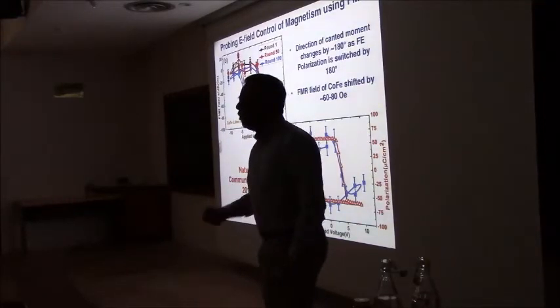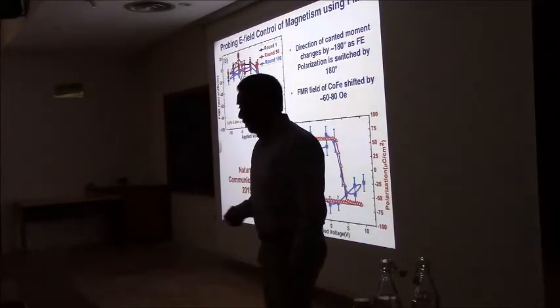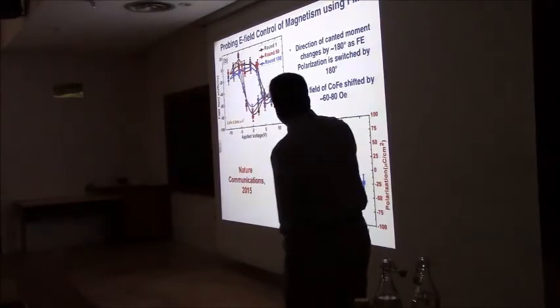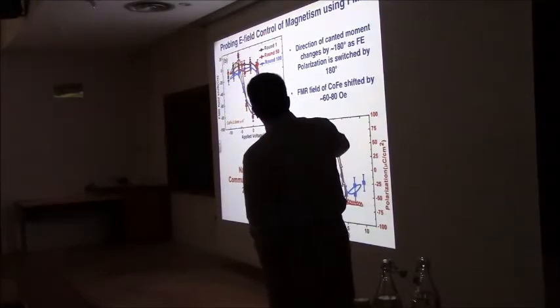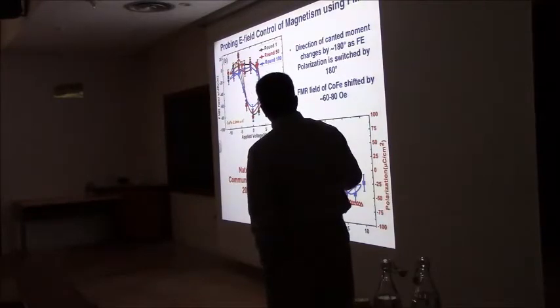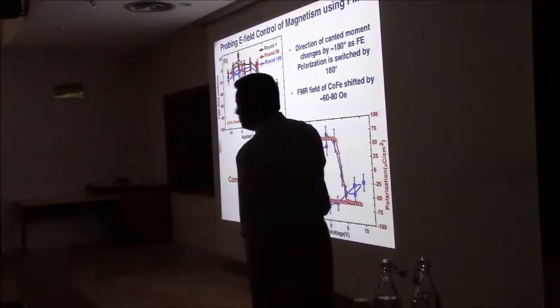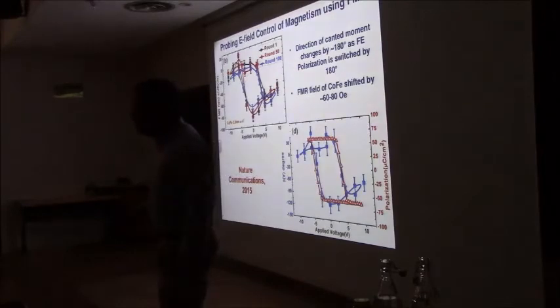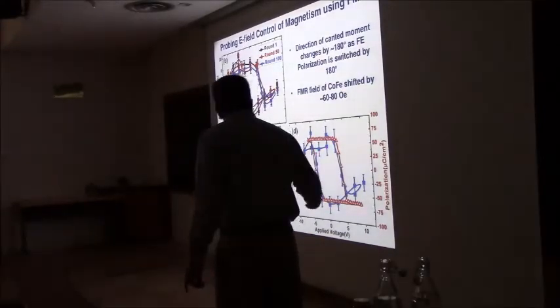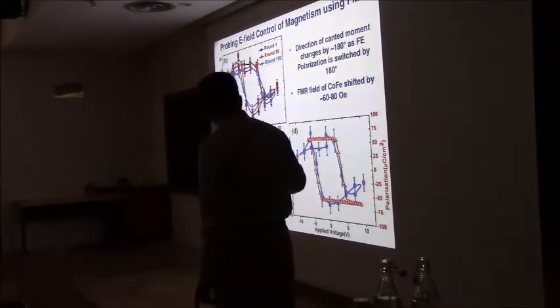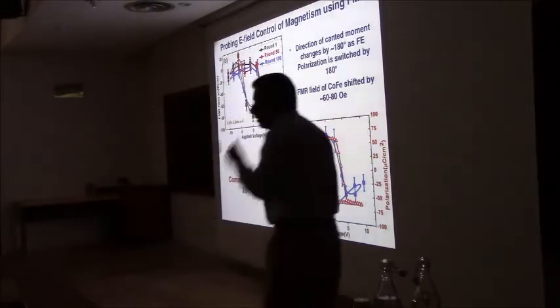So you can see the FMR resonance line shift is of the order of 80 oersteds. Ideally, you want it to be an order of magnitude larger to be really useful in application. But you could see that it was quite robust with 100 cycling, and it was going back and forth in hysteresis. You can extract from this by using time-dependent Ginzburg-Landau models the direction of the canted moment. And it says that it switches approximately about 180 degrees. And it overlays very well on the ferroelectric switching.